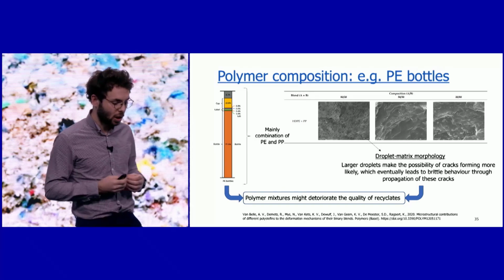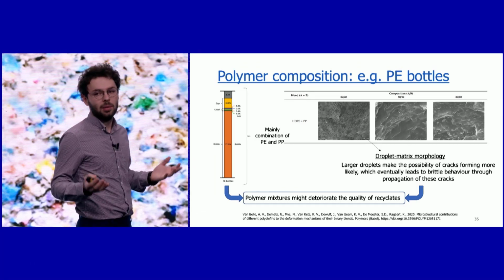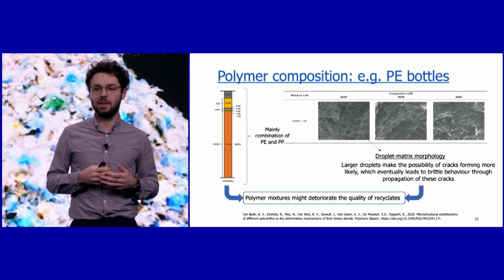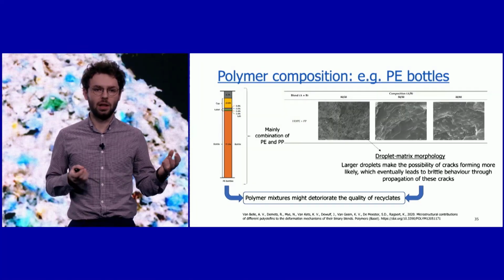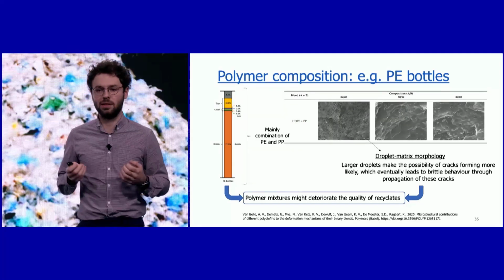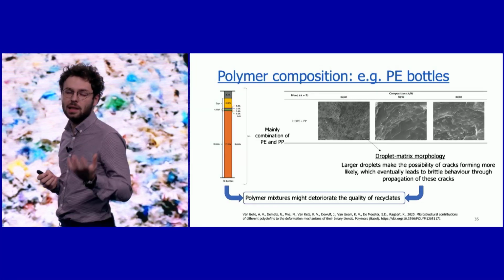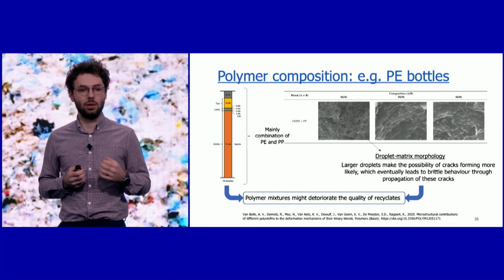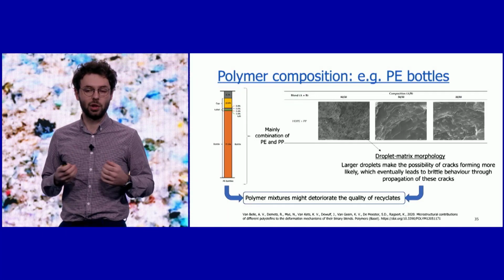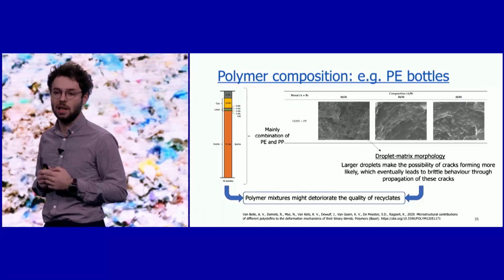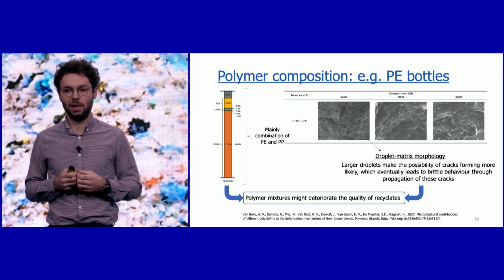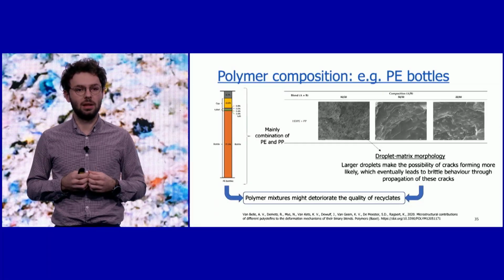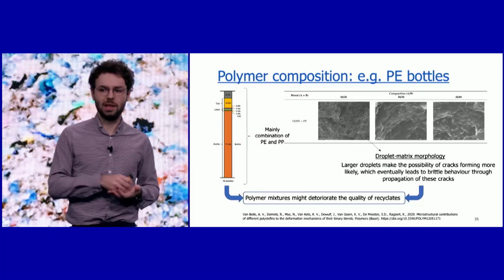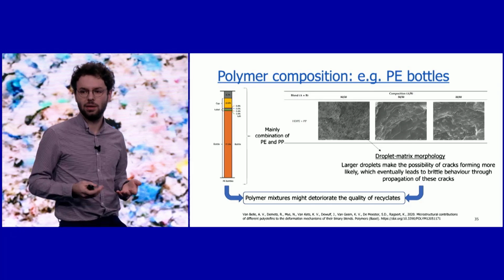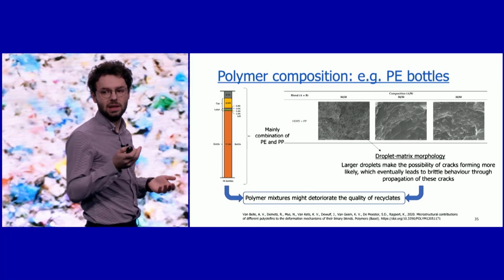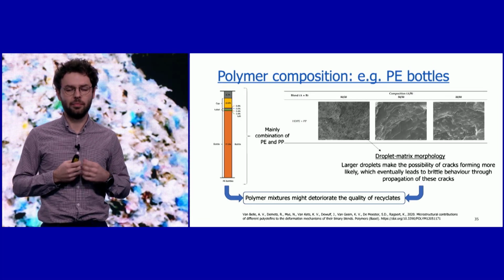This polymer composition is very important for mechanical recycling, because what we see is that if certain polymers are blended together, this can deteriorate the quality of the recyclates produced. This can be explained by the morphology of those blends, which sometimes have a droplet matrix morphology, which can induce propagation of cracks and brittle behavior.